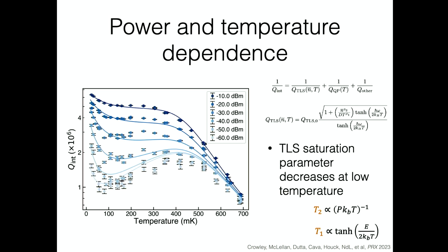Okay, so now the key thing here is that one of these free parameters, this prefactor on the two-level system loss, now looks a lot like a materials parameter, because this little prefactor is basically the linear absorption due to two-level systems. So this is very intriguing because one of the real pain points in this field is how do I compare apples to apples? If I do a measurement and I cool down my qubit and I say I can get a T1 of 400 microseconds, and then Rob Schoelkopf tries to do the exact same thing at Yale, and he cools it down, and he's like, "You're a liar. I only see a T1 of 100 microseconds."